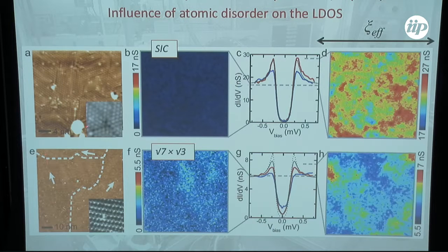And indeed, we repeated these experiments, and we observed a gap, which is very clearly similar to what BCS predicts. And this gap is very interesting because on atomic scale, as here, you see the small balls are individual atoms, and what you see here and here are the gap maps, so it's the density of states of the same area. On the left side, you see the depth of the superconducting gap. So this is typically the density of states at zero energy. You see that the gap exists everywhere. It is blue, etc. And here is nothing more than the height of the quasi-particle peaks.